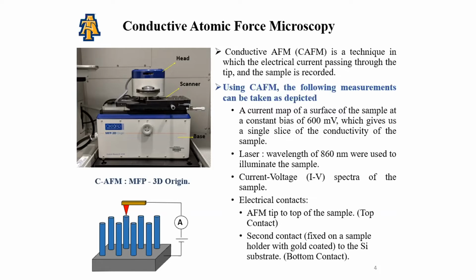It has to be noted that the tip radius should be lesser than the feature we are scanning for high spatial resolution. To illuminate the sample, a laser of the wavelength of 860 nanometers was used. Current mapping under a DC bias of 600 millivolts is done. Top contact is the AFM tip to the top of the sample, and bottom contact is the gold-coated contact connected to the silicon substrate.